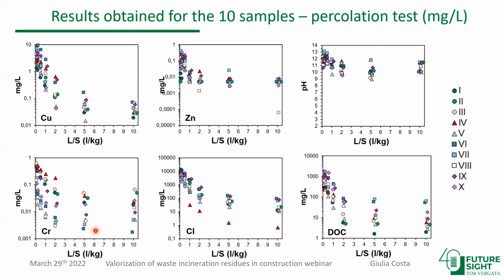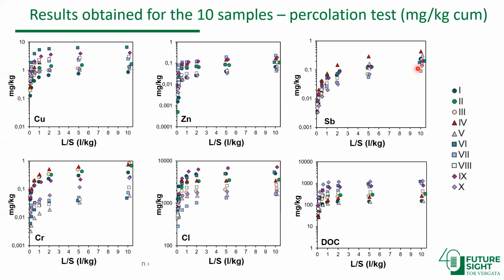We see a larger variety here in the case of chromium, where samples from plant C show the lowest release, whereas the ones from plant A and the coarser one of plant B show a higher release. This is interesting to evaluate the pH. So the pH of the percolation test leachates went from 13 to around 9, and generally decreases until a liquid to solid ratio of 2, and then sort of stabilizes. Highest values were found for the sample in which cement was added.